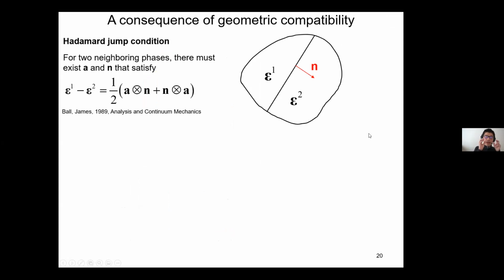So you can actually very nicely explain this as a consequence of geometric compatibility. Let's recall this so-called Hadamard jump condition in classical linear elasticity. It tells you that if you have two domains with different phases and with different strain fields, then there must exist two vectors that satisfy this equation, which allow these two domains to be compatible with each other. Otherwise, there will be some fracture or dislocation, a discontinuity across this boundary. This equation is really a consequence of the continuity of the displacement field. The displacement has to be continuous when it crosses the boundary, but the gradient of the displacement, which is the strain, doesn't have to be continuous, right?